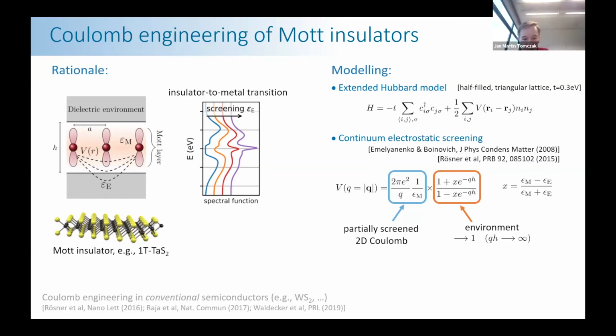Yes. Okay, so here we had a hopping of 0.3, which is maybe too large for this system. And what I showed in the modeling here was with respect to the freestanding case, so that you put the dielectric environment from both sides directly on the monolayer. But we have, I think it's in the appendix also, where we look at one-sided screening. If you have this thing on top of the substrate, then first the substrate modifies the monolayer, and you only have control over one side. You can only tune or change the screening from one side by putting a dielectric on. So then the effect will become weaker as well. Okay, thank you.